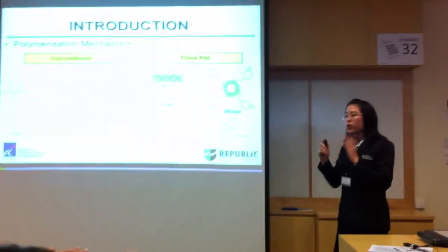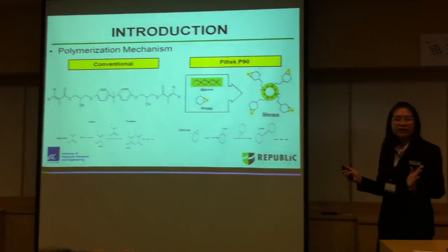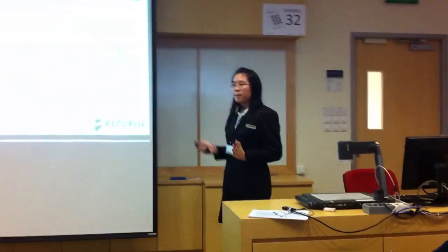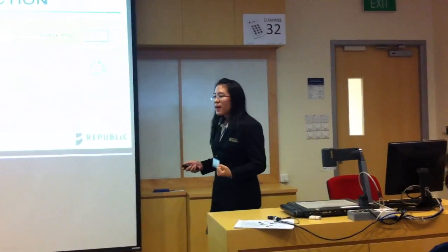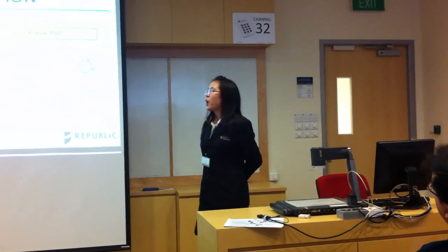As the oxirane consists of a ring, you have a ring opening mechanism during polymerization. And this ring opening mechanism will eventually be able to compensate for the volume shrinkage, minimizing the volume shrinkage as well as the polymerization shrinkage.